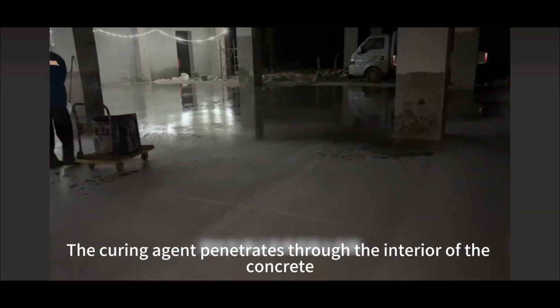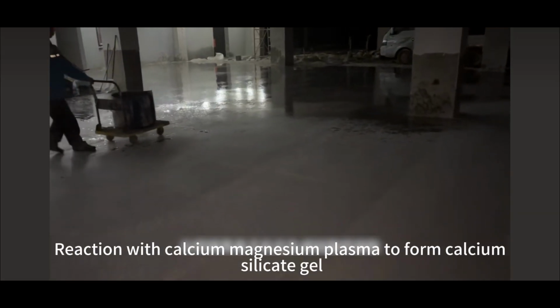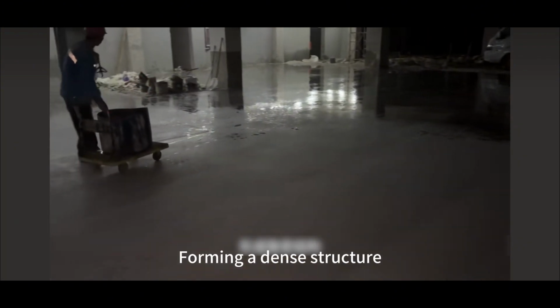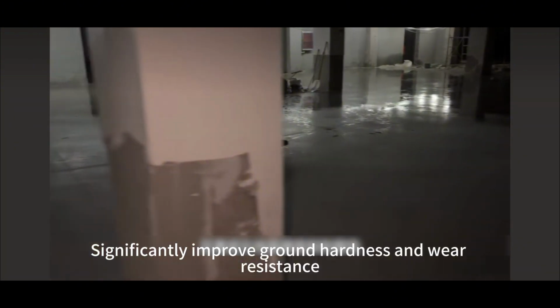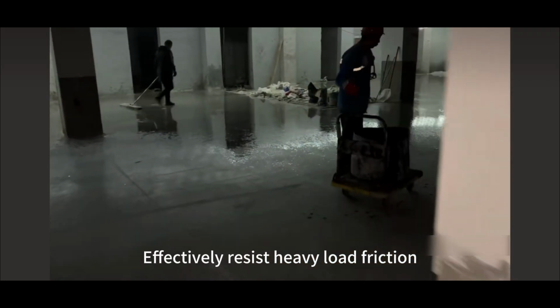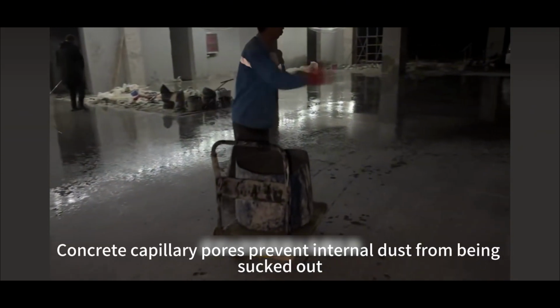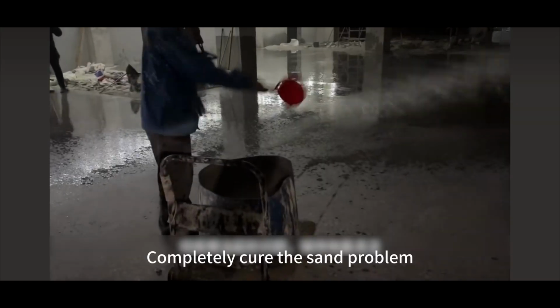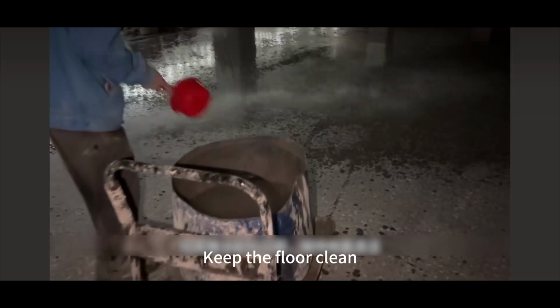The curing agent penetrates through the interior of the concrete. It reacts with calcium-magnesium ions to form calcium silicate gel, forming a dense structure. This significantly improves ground hardness and wear resistance, effectively resisting heavy load friction. It can also seal the concrete capillary pores to prevent internal dust from being sucked out, completely curing the sand problem. It keeps the floor clean while increasing the coefficient of friction and improving anti-skid performance.